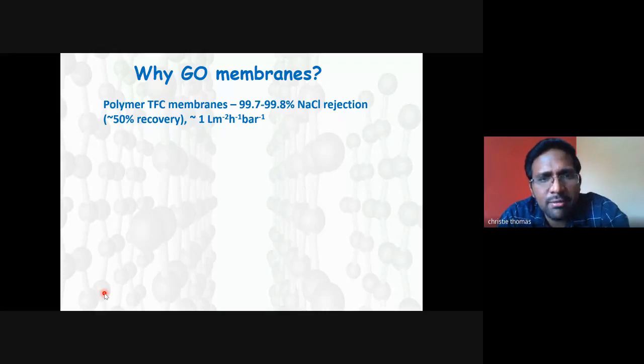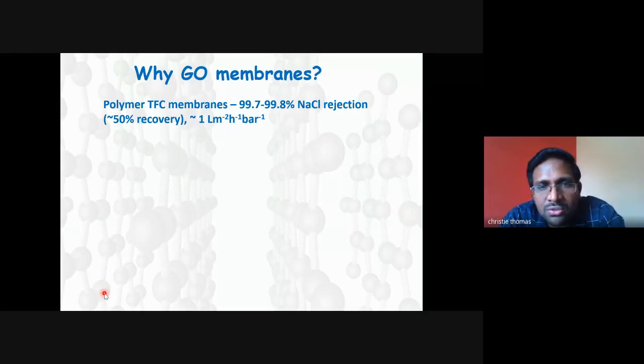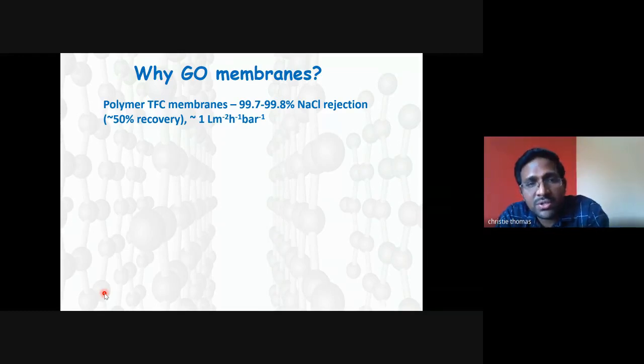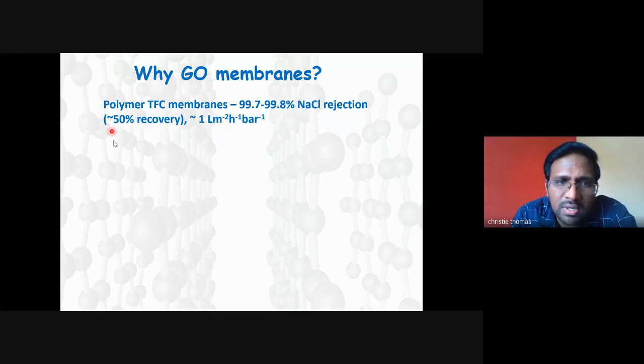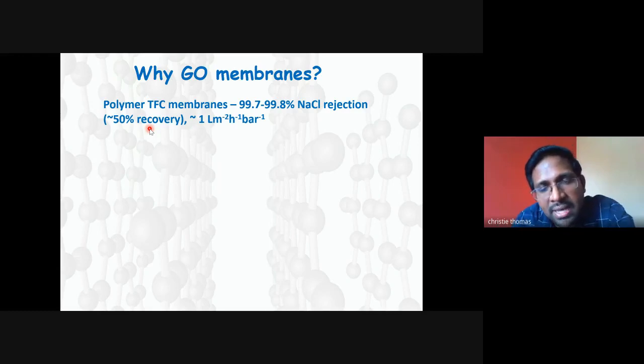So I'm winding up by telling you the prospects of GO membranes. In industrial-scale desalination plants, we use polymer thin film composite membranes, polymer TFC membranes, having 99.7 to 99.8 percent sodium chloride rejection, and 50% recovery, and the flow rate is 1 liter per meter square per hour per bar. What do you mean by 50% recovery? If any one of you are using a filtration unit in your house, you can see that a lot of water is wasted as a byproduct. You get pure water as well as wastewater. So 50% recovery means 50% of input water can be recovered.